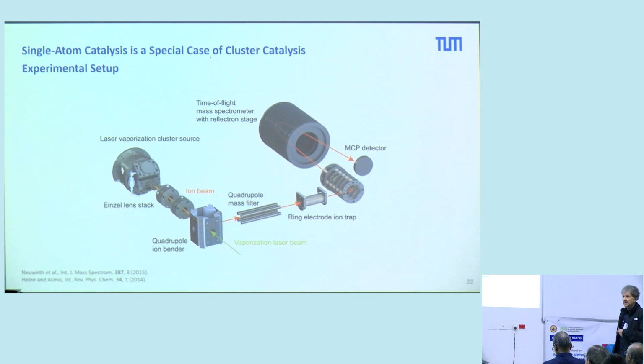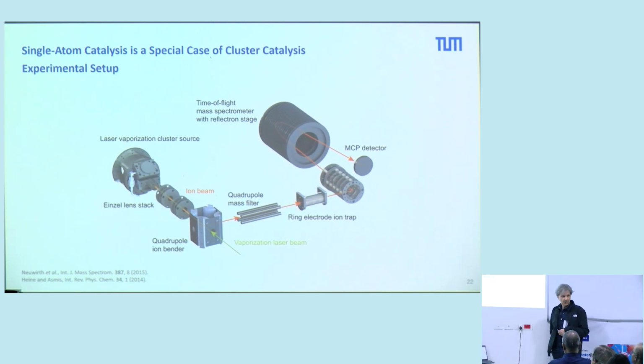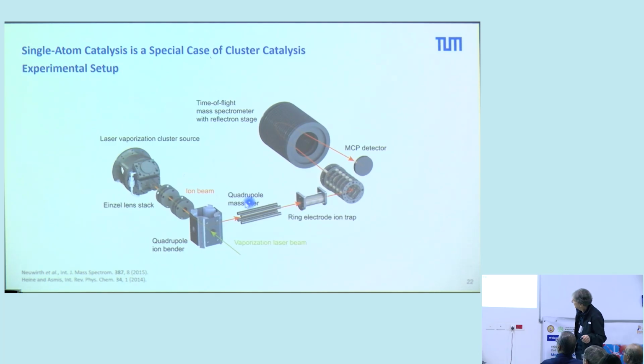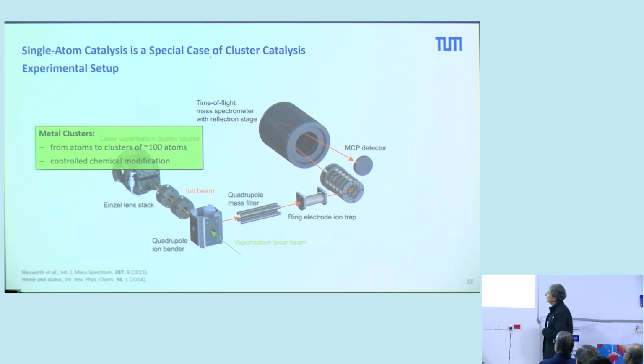If you would like to study single atoms, as the word tells you, you have to study single atoms. And this you can, of course, do only in the gas phase. And our experimental setup is shown here. We have a laser vaporization source, we have ion optics, we have a quadrupole mass spectrometer with which we can select a single size, and then we can put these clusters in an ion trap where we can do chemical reactions. We can heat and cool down this ion trap so we can get information on kinetics. And then the products, after a given time, we can analyze with a time-of-flight mass spectrometer.